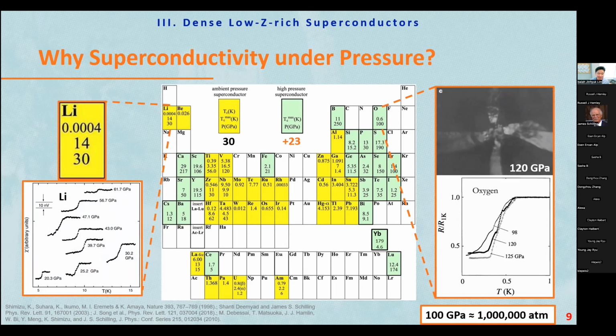Another good part of using pressure is that in the lithium case, you will see a tremendous increase of TC when you apply pressure. At ambient pressure, TC is 0.4 millikelvin, a very low temperature. But when you apply 30 GPa, it increases tremendously to 14 Kelvin. So that is 5 orders of magnitude of increase. So pressure can enhance the superconductivity.